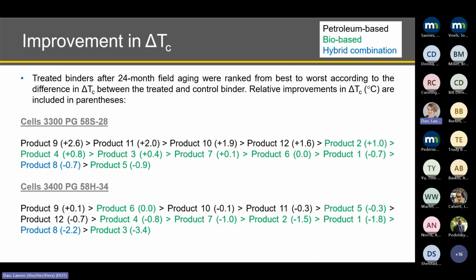The first set of data is related to the surface with a PG58S-28 binder, where the second one is the polymeric binder 58H-34. You can see by the color coding that for the 58S-28, the products that are more effective in improving the delta TC of the control binders were the petroleum-based ones. And for the polymeric base, we had a mix, with the best products being petroleum-based and bio-based.